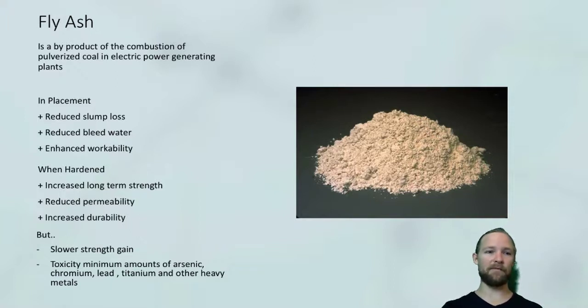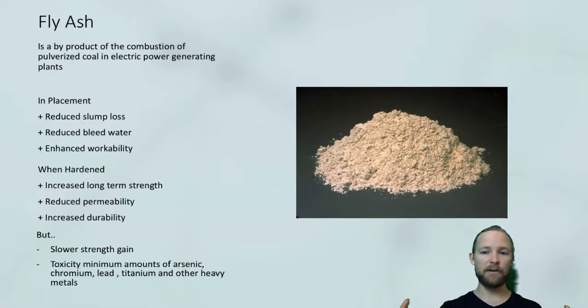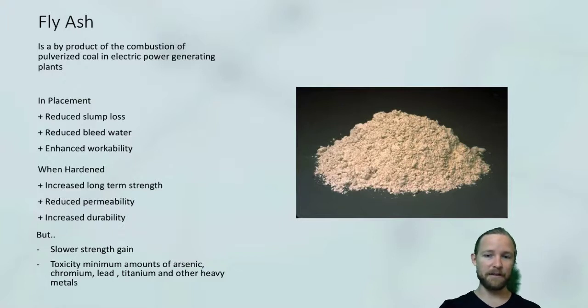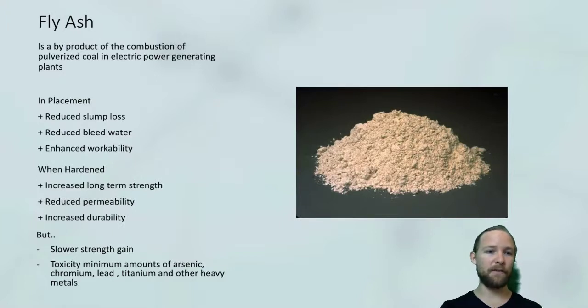Where can you apply fly ash, or where is it most suitable on a project? It is probably where low early strength is not so critical. If you look at shear walls, for example, they're not going to be loaded early. Foundation elements, because as you construct the building, there won't be significant load until later in the construction program. Anything not subject to high load in the first few months is suitable for a high proportion of fly ash.